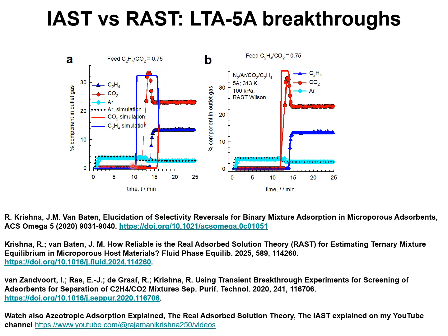The breakthrough simulations using the IAST are shown here by the continuous solid lines, blue for ethene and red for CO2. The IAST anticipates that the last component to breakthrough is CO2, whereas in the experiments, the last component to breakthrough is C2H4.